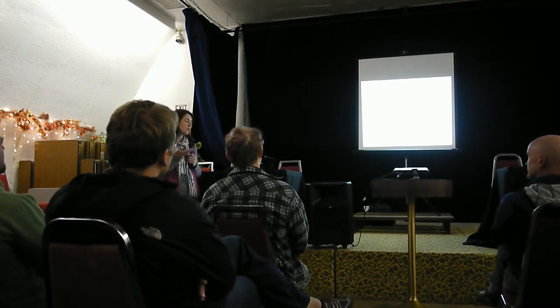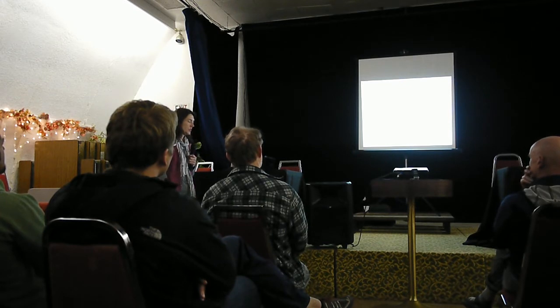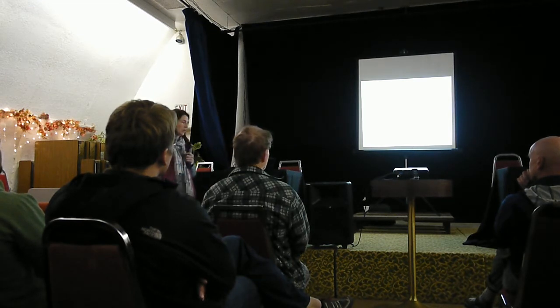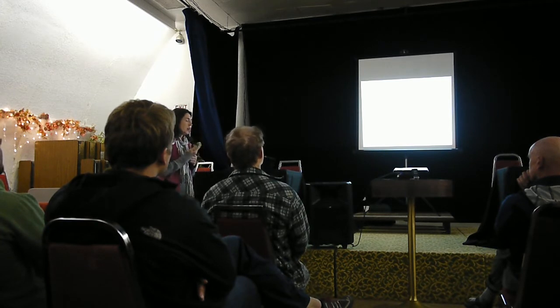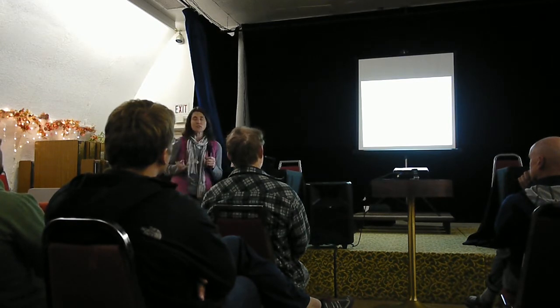So I told you, you need a material that's susceptible to stress corrosion cracking in the first place. Things like titanium grade 2 in certain corrosive environments like the one in Thailand, it's just not going to happen. But with the stainless steel, the 316, if it sees chloride ions above a certain level, and there's enough stress in the material, where there's some sort of a tensile stress with the pencil hanger, it had been cold worked and there was a bend in it, because there's bends in all hangers.